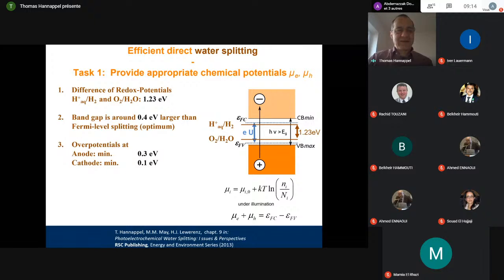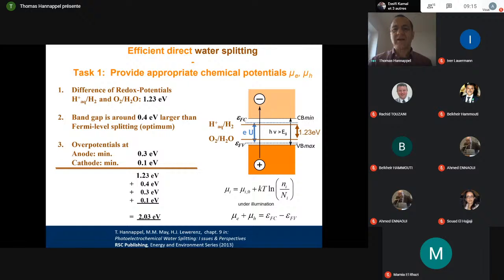Thirdly, we need to see that at both electrodes, at the anode and cathode, we have to create a so-called overpotential. This depends strongly on the catalyst which we are using. This catalyst normally, in the best way, provides overpotentials which are larger than 0.1 eV at the cathode and 0.3 eV at the anode. And this we also need to add. If we sum up everything, we see that we cannot get better at needing a semiconductor energy gap of more than 2 electron volts. And this is exactly the challenge now.